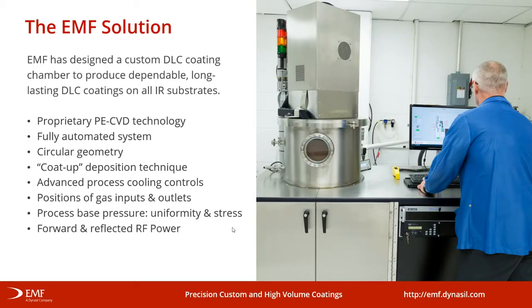EMF has designed a custom DLC coating chamber to produce DLC coatings. We use proprietary plasma-enhanced chemical vapor deposition technology. It's fully automated. It has a circular geometry to improve uniformity. We coat up, which is unique in the industry, meaning that any excess material falls down away from the optics rather than on top of the optics, which reduces the number of pinholes. And we've done advanced process control on the cooling and the positions of the gas inputs and outputs, all leading to a superior coating.